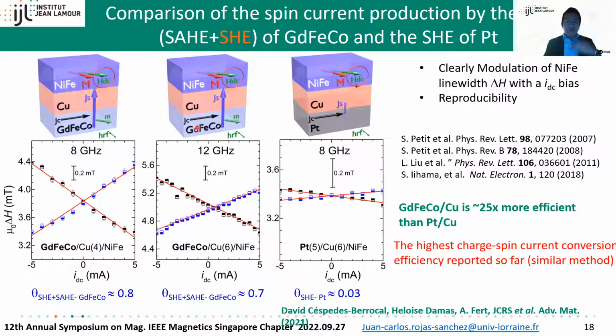We measured other devices. My colleague made another trilayer, and again the value was large. So then I waited. Fortunately, at that time our sputtering system was out of order, so I had to wait several months. Finally, we got this platinum copper permalloy grown under the same conditions, the copper and permalloy in the same sputtering chamber. We also observe here a nice variation of this line width, and the quantification is reasonable for platinum. So then we were confident that the previous results in this GdFeCo were okay. We measured this again after several months, or one year, and we find the same variation and the same quantification.